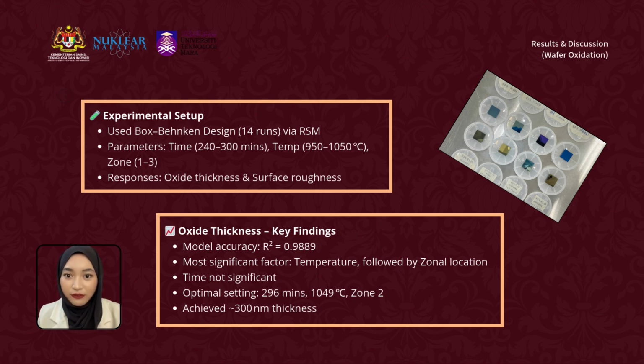The most significant factor was temperature, followed by furnace zone, while time had little impact. The optimal condition was identified as 296 minutes, 1049 degrees Celsius, and zone 2, which successfully produced an oxide thickness of around 300 nanometers. This was also supported by the RSM report, which confirmed these settings as optimal.